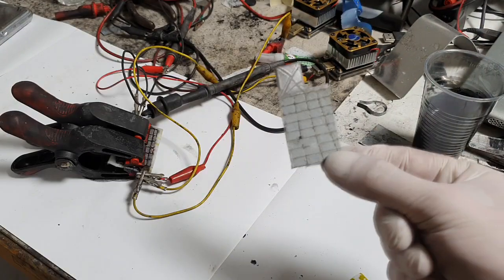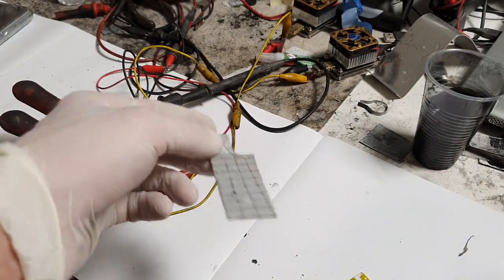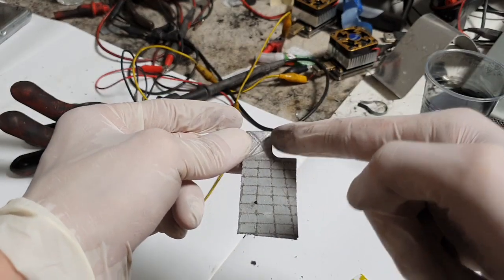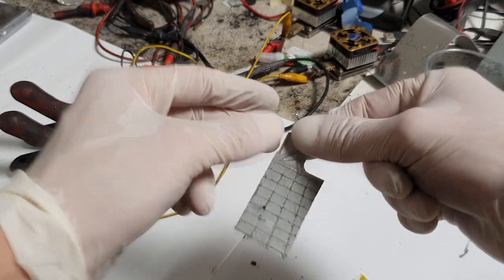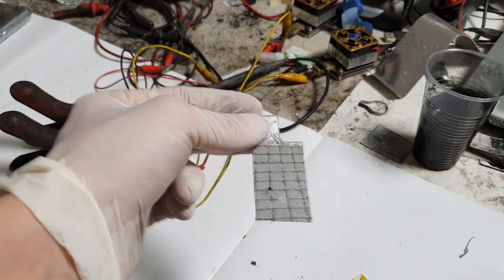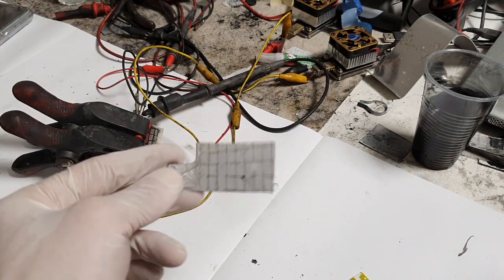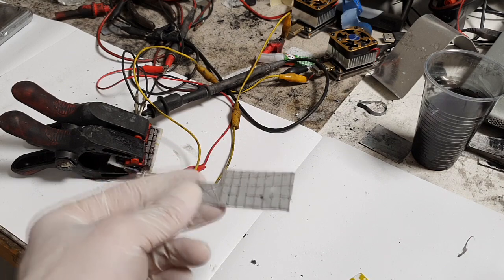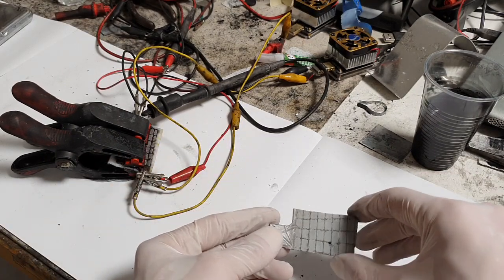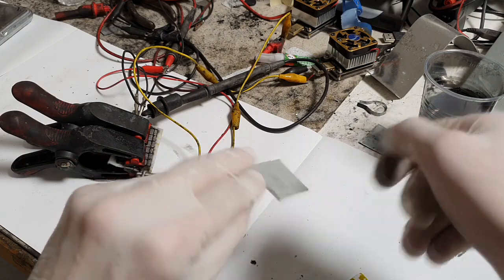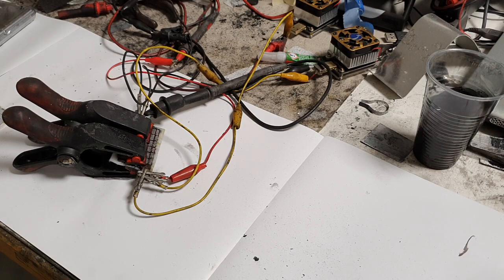So here I have the negative electrode of lead acid battery. So in basic, it's lead current collector, I mean lead grid current collector, and the active material is lead powder. To modify this type of electrode, you simply make an ink from activated carbon and paint it over the entire surface. You see that you can modify a lead acid battery really, really easy. You just put some carbon-based material on the negative electrode and you will increase the performance. So in this case you will increase the cycle life and also the charging speed of this battery.